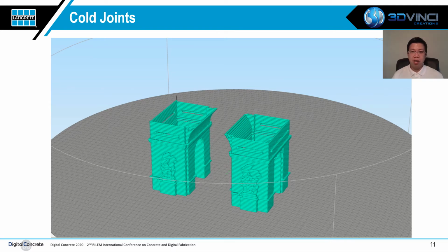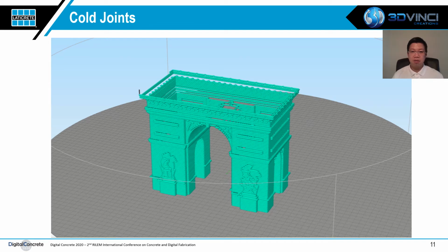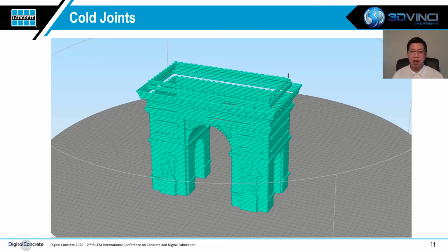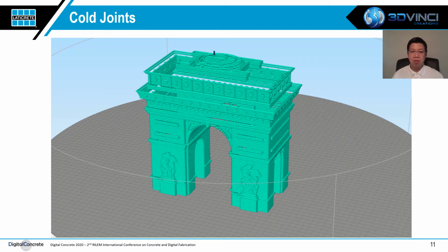For example, here, if we want to print the Arc de Triomphe, we may not be able to print it in one run, but instead we would print it in several steps within an extended time. For example, we may print 1 to 2 meters tall per day and then continue to print the next day and so on until the structure is completed. In this case, the interface between two layers that are printed on different days acts as a cold joint.